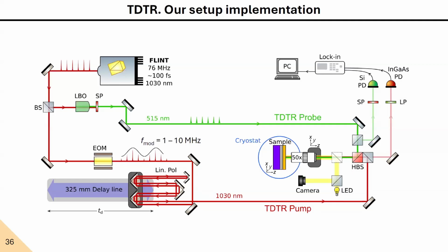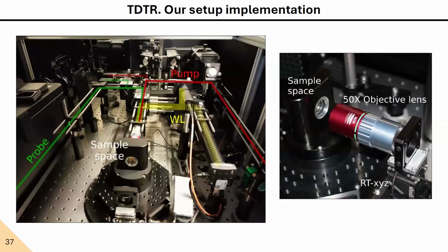Both of these beams recombine at an objective which focuses the light on the surface of our metal transducer. The reflected light, we take it into a silicon photodiode, and we demodulate the signal using a lock-in amplifier. We also have a white light imaging system to visualize our sample and to know where we are performing our experiments. In the lab, it looks like this. It is very complicated, but mainly you see the two laser lines recombining and eventually going into our objective, which focuses onto our sample. And our sample is here inside the cryostat, which allows us to control the temperature. The reflected light is guided to our detector.